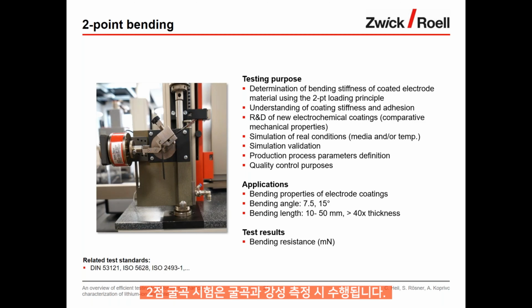The two-point bending test is used for the determination of the bending stiffness, and it's used to characterize the behavior of coated electrodes during the production process. So we are bending the coated electrode up to 7.5 or 15 degrees, and can determine a bending resistance, which gives us information about the bending stiffness of the sample. And again, this test is used to understand some relevant process parameters and helps to improve the quality and efficiency in the production process.